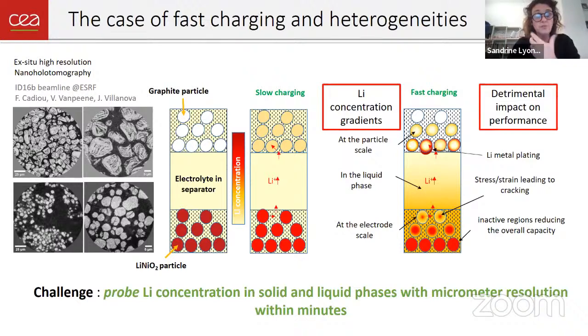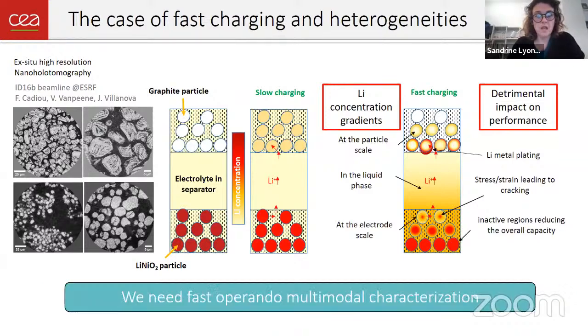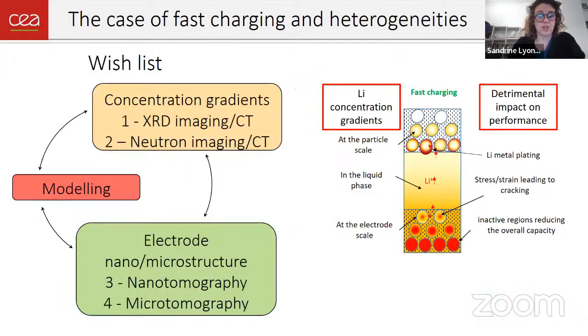So what we want is probing the lithium concentration in the solid and liquid phases. And we want to do that with a micrometer resolution. Electrodes are typically 50 microns thick. And we want to do that within minutes because we typically want to charge a battery in 10 or 15 minutes. So we need fast operando multimodal characterization to address this challenge.